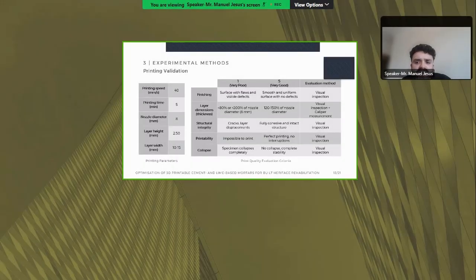To avoid the structural failures previously discussed, the printing parameters had to be standardized and are presented in the table on the left. Using an 3 millimeter nozzle and a speed of 40 millimeters per second, each specimen was printed in about 5 minutes, and a layer height of 2.5 millimeters and a width of 10 to 15 millimeters was achieved. These settings provided the stability needed to prevent plastic collapse or nozzle clogging observed during the initial calibration phase.